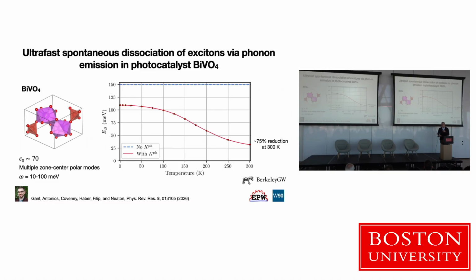And this very large reduction has to do with the fact that there are multiple polar phonon modes that are very low energy, about the energy of the exciton. And so essentially you've got a polar phonon that is oscillating about the same period as the Bohr orbit. And so that really reduces it. There's a strong, frequency-dependent interaction there that leads to this reduction.